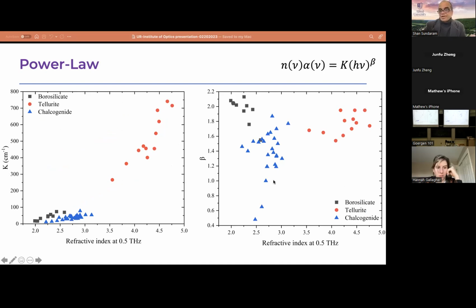So you can see for glasses, the beta value is supposed to be just 2. This from the physics, they just come up with the power law fitting. But our data clearly shows it's just not 2 at all across the board. There's a whole range of beta values depending on what glass composition you are looking at. We noticed if you're talking about silicates and purely common oxide glasses, you're probably approaching more like a 2 value. But if you're looking at tellurite, you are getting about 1.5, around that range. And if you're looking at chalcogenides, because of their layered structure, various combinations of structural units are possible, you're getting indeed a whole range of beta values for that.